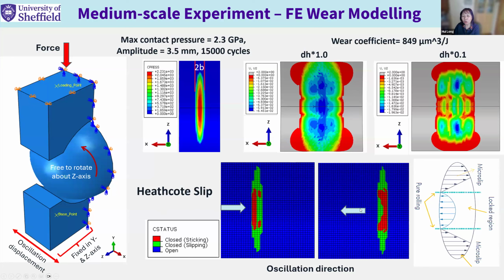These two images show, when the ball is moving over the raceway surface, how the slip regime and the stick regime vary. You can see the green areas are the slip regime. Because of the higher micro-slip regime, they contribute to greater wear in those regimes, as shown in this FEA result. You can also see a line here with smaller wear depths. This is because in those regions we have pure rolling.